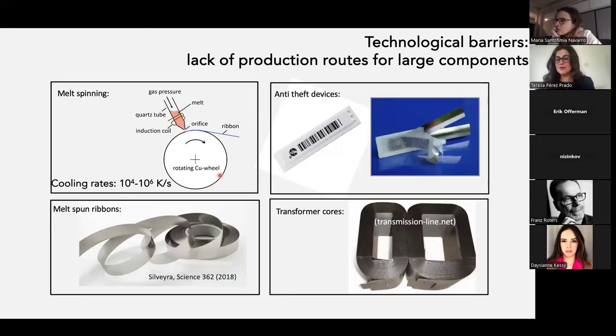This problem is particularly pronounced for the alloys that have low glass formability, which means that even if we cool the liquid metal very, very fast within that range, there is a maximum thickness that we can make in amorphous form. For the materials that are of interest for this talk, the glass formability is only between 100 and 150 microns. This is very, very small, and almost the only method that we can use to produce these materials in amorphous form is melt spinning.